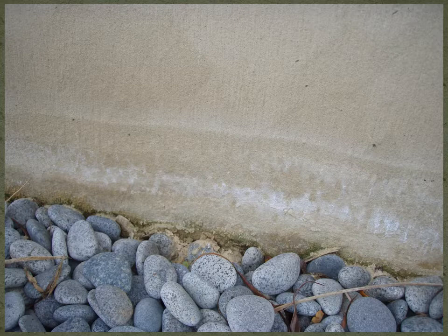This is rising damp in a limestone facade. You can see on the little pebble stones down below the actual material of the limestone. You can see efflorescence, that white line that's forming from the moisture. This is because this limestone has been overlapped by landscaping soil that's getting overwatered, and it's wicking up into the stone, causing all these problems. It should have been waterproofed or should have received some sort of flashing that would protect the limestone from this moisture. This is the stone, by the way, this is a striated finish, which we talked about before, and which you don't see very often.